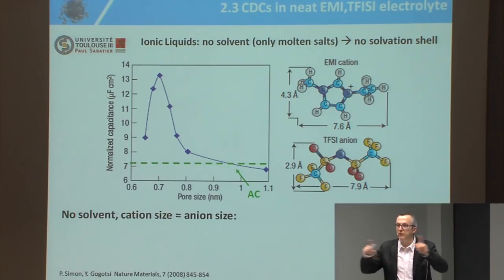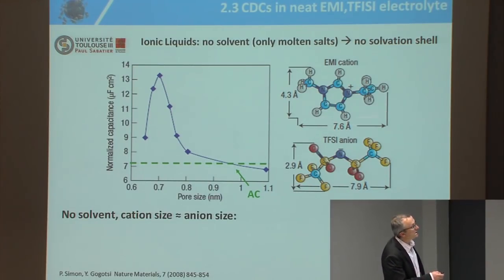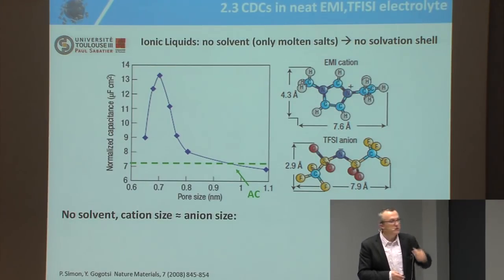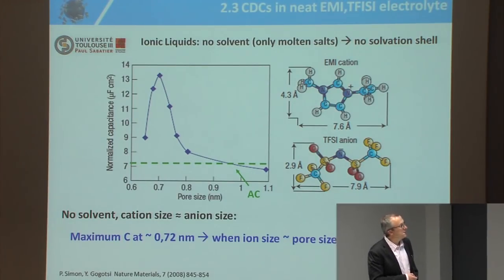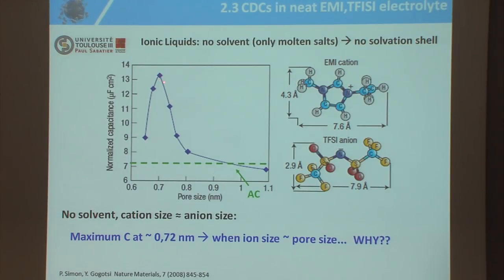There is no solvent, no solvation shell. And you can see the size is about 0.76 nanometer, 0.79 nanometer. And when you study the capacity of our carbons in these ionic liquids, with a carbon which has a pore size of 0.72 nanometer, you have a maximum capacitance. And this was a very important message: when you don't use any solvent, you maximize the capacitance when the pore size is more or less equal to the ion size. So it was also a very new concept for preparing materials.